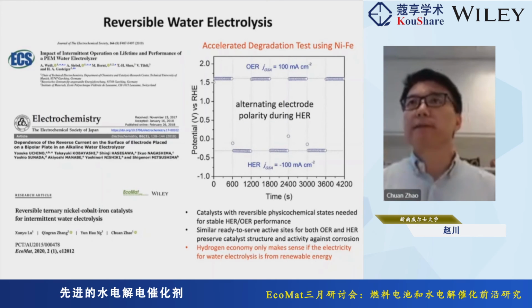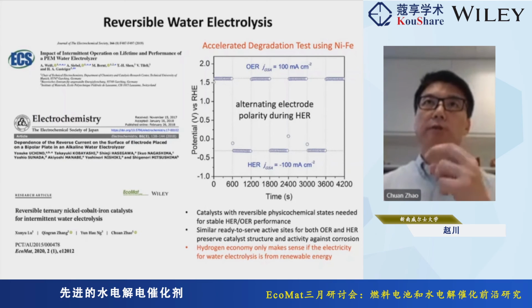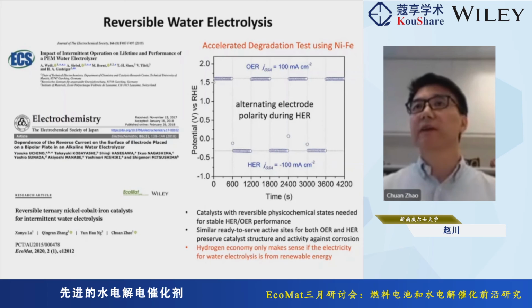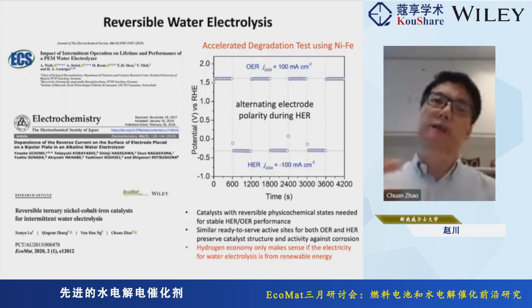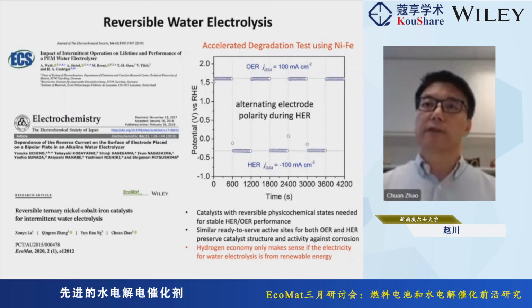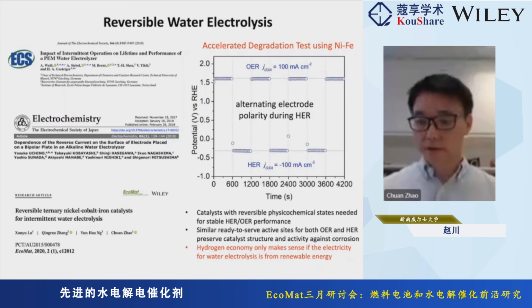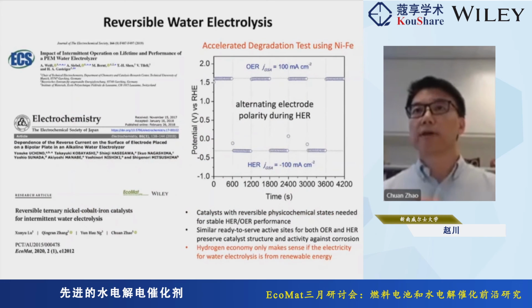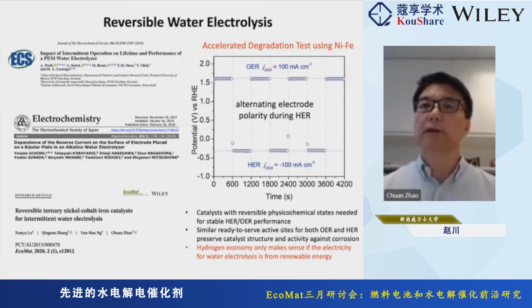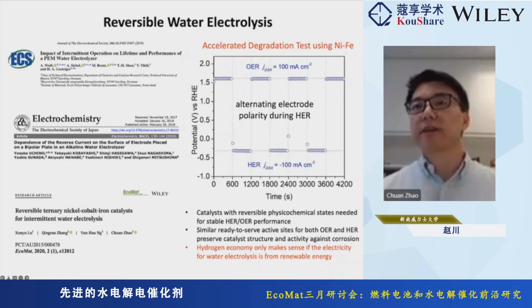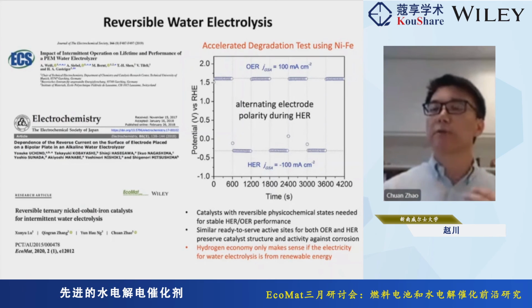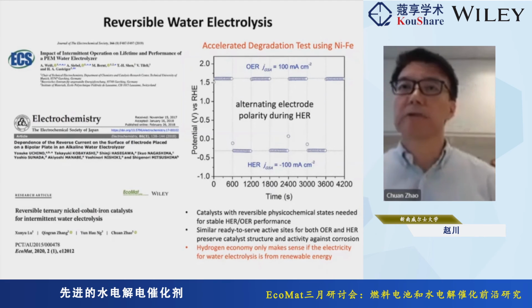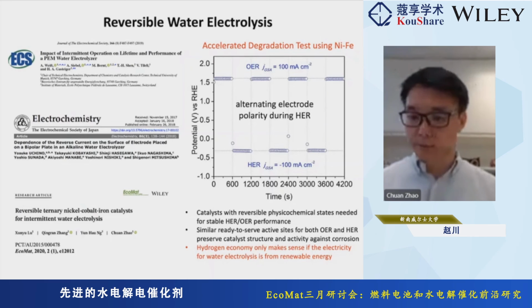We also tested this nickel iron HER catalyst for the reversible water electrolysis condition. What we did there is mimic the shutdown and startup process of the electrolyzer, basically switching the polarity of the working anode and the cathode during electrolysis. We found quite stable performance of the catalyst under these intermittent conditions. So the message is, if you have a catalyst with a reversible physicochemical state, it is more likely to have very stable water electrolysis performance.